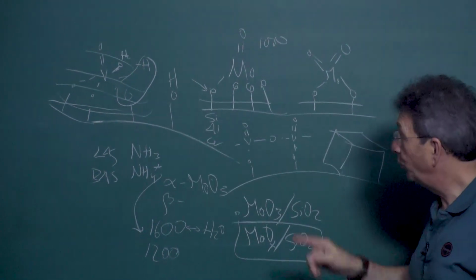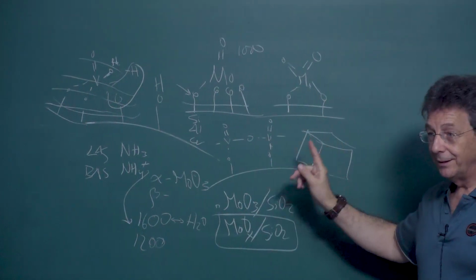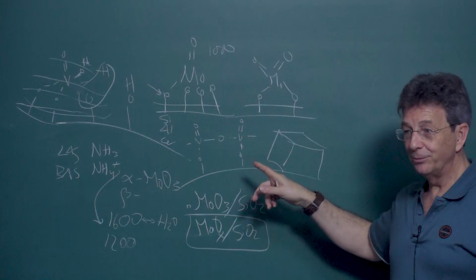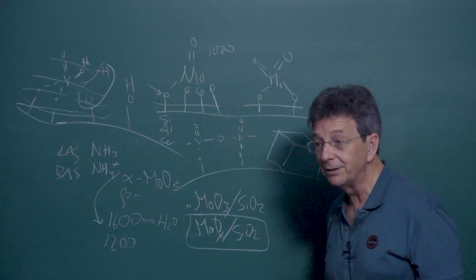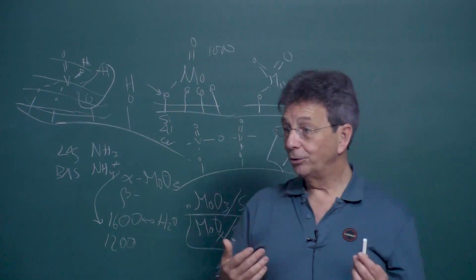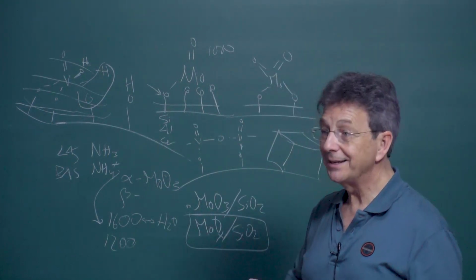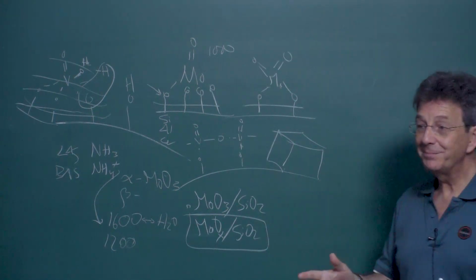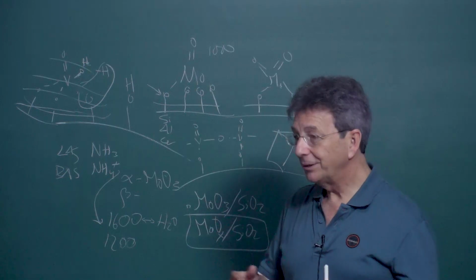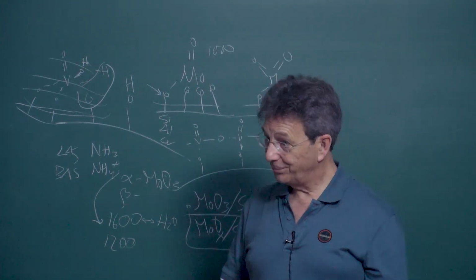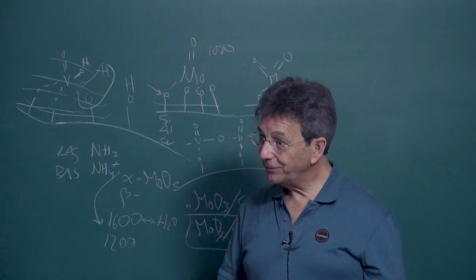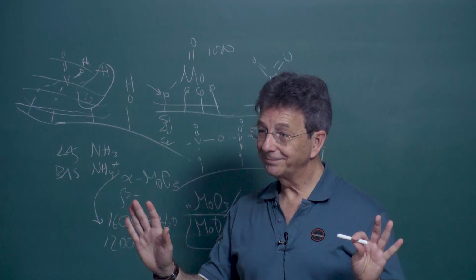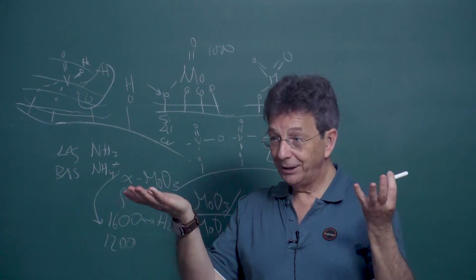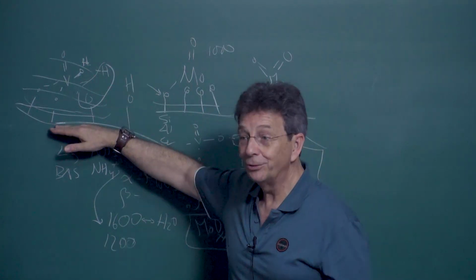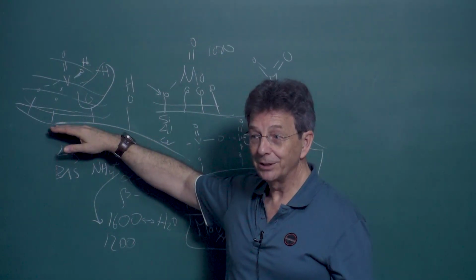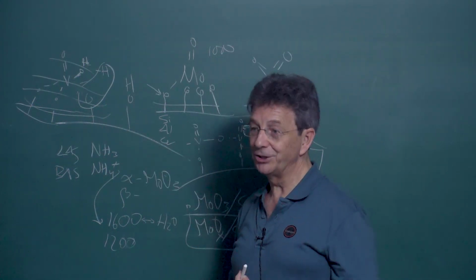And what kind of structure do you have under ambient conditions? Liquid phase chemistry. If you go to an analytical chemistry book and look at what phase of molybdenum, vanadium, chromium, whatever you will have, you will see that it depends on the concentration and on the pH. Exactly the same thing happens there. Gautam got amazing Raman spectra of all the samples of vanadium, molybdenum, and different oxides on different supports. Depending on the support and the coverage, you change the concentration and the pH. It perfectly matches. Now you heat, the water evaporates, and then what happens? The oxides go back to the support and again become molecularly dispersed, because everything is dry. So this is a completely reversible change.